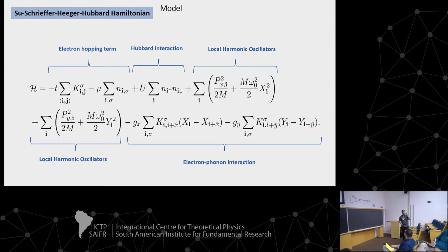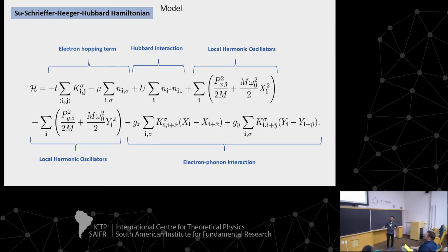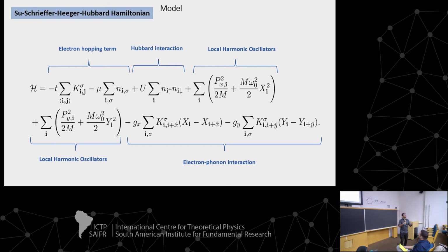And there is one very interesting thing here. And this is something that I can ask you if you want. Do you know why we don't have high temperature superconductivity for conventional phonons? The question is the mass of the polarons. Because if you increase more and more the electron-phonon interaction, the BCS theory would like to increase more and more the critical temperature. But you pay a price. When you increase more and more the electron-phonon interaction, your electron, dressed by your phonons, becomes heavier and heavier and heavier, and then you cannot increase the temperature. This is the basic idea why you don't have high temperature superconductivity mediated by phonons.